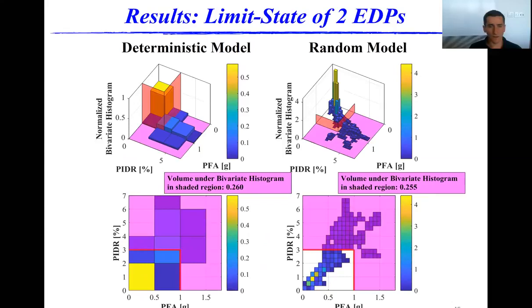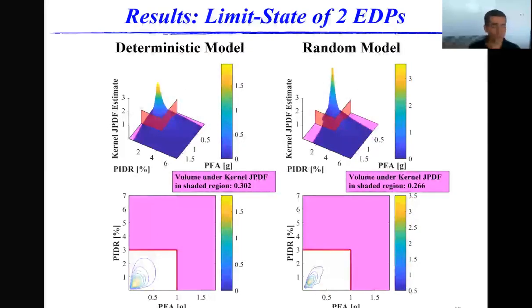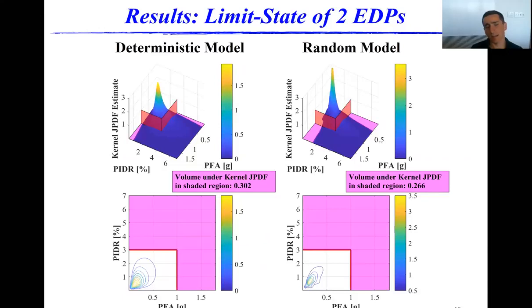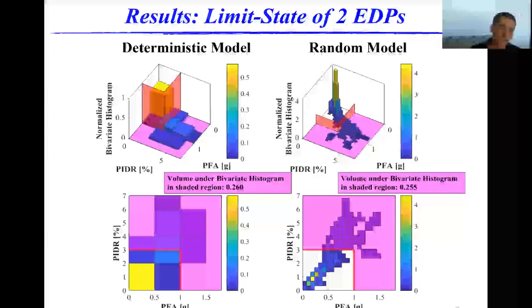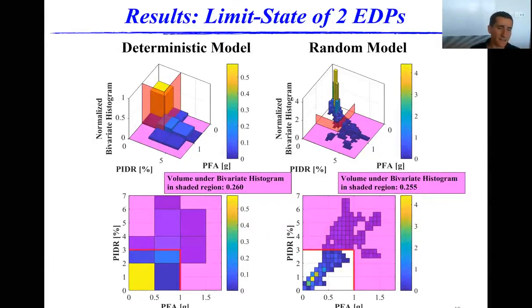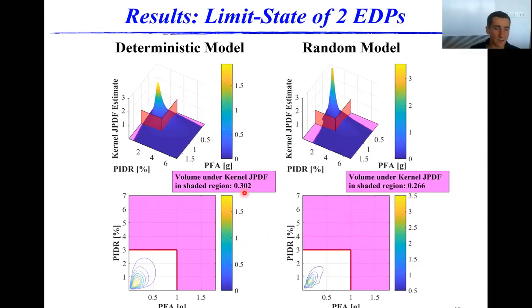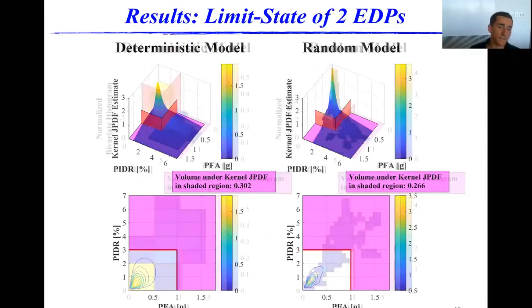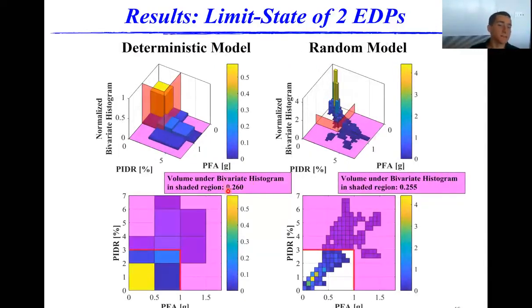And like we did for the univariate case, we can fit some joint PDFs by kernel density estimation to these histograms to get an idea of the dispersion. So what I want to quickly note is that for the random case, the kernel density estimate is 26.6% chance of exceedance versus 25.5%. On the flip side, in the deterministic case, the kernel is estimating 30.2% versus 26% from the histogram. So again, we're seeing a greater discrepancy in the deterministic case, which is due to the small sample estimation uncertainty.